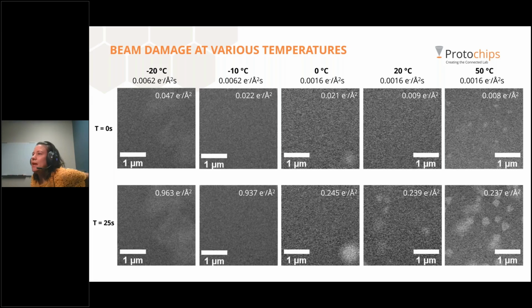We saw that behavior, thought that there was a trend with that, but after going back through the data and pulling that information out of it, we see that there is a correlation between beam-induced damage and increasing temperatures and vice versa. Now I'll say a caveat to these slides here.